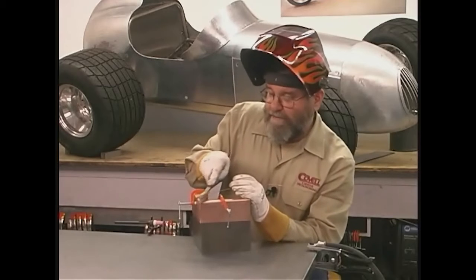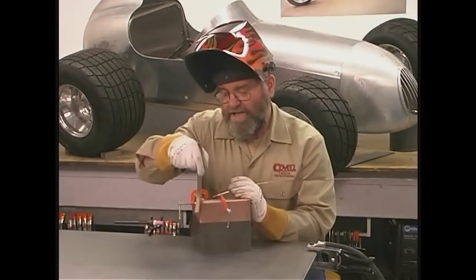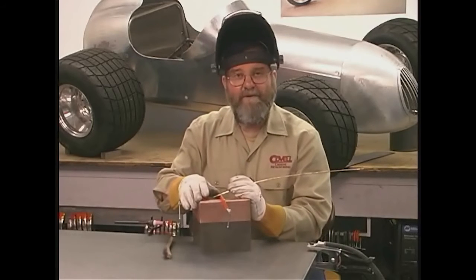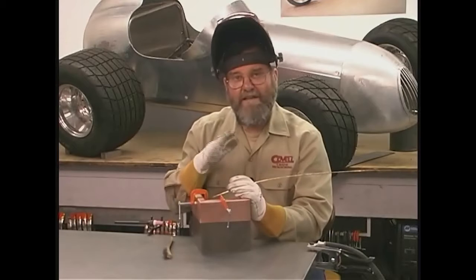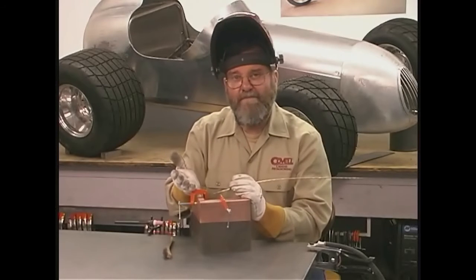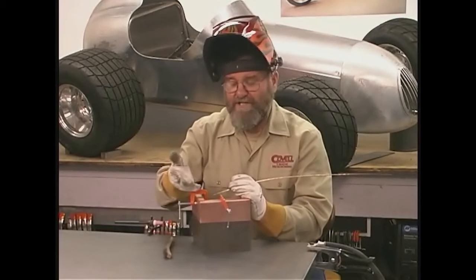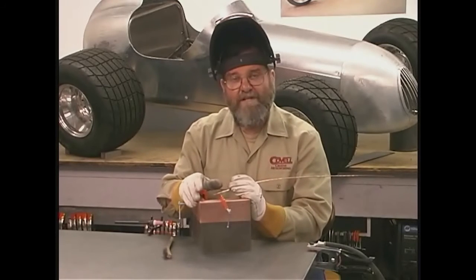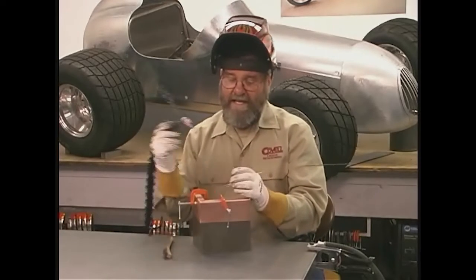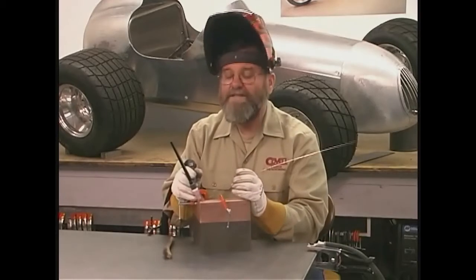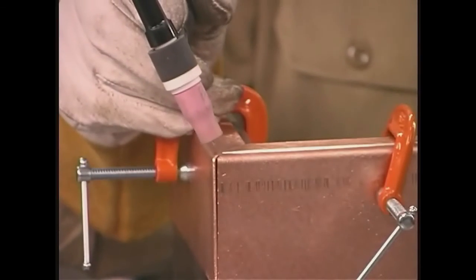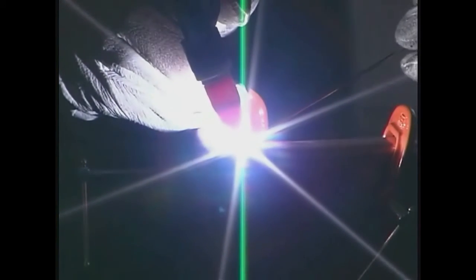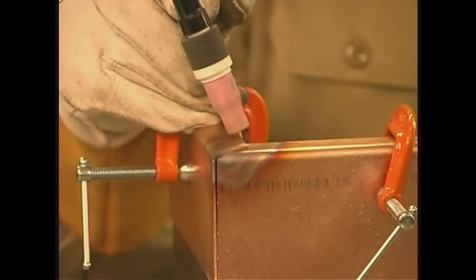So let me clean this joint in preparation for welding. One more thing to mention, one limitation for welding copper is that copper is a tremendous conductor for heat. So it takes a lot more heat input to form a puddle than with any other metal. So that means you just have to crank up the amperage on the machine, and once you've done that, you can successfully weld copper. So I'm going to form a puddle and start dipping the rod into it, and we'll join these pieces. Okay, then we'll rotate this piece so I can reach the other portion.